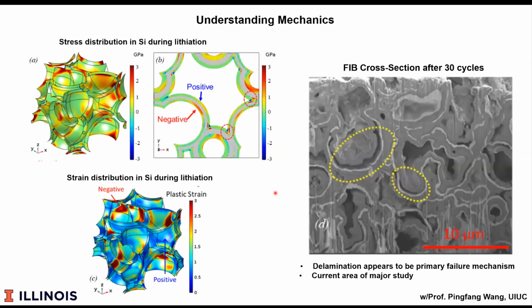To accomplish that, we have some great collaborations. Here's some data taken by my student Nathan Fritz. And it's a collaboration with Professor Pingfang Wang, also at Illinois, and what he's been modeling the strain and mechanics in the system. What we observe is indeed that you see here's the metal. We do indeed observe some delamination effects after cycling, and this is because of this swelling and deswelling. So while we have high capacity, we can get high charge. Mechanics are now becoming, I think, one of the key factors to understand.